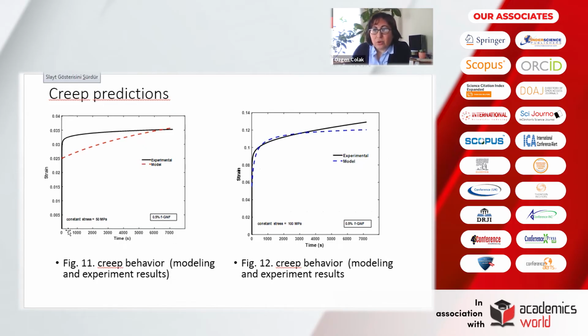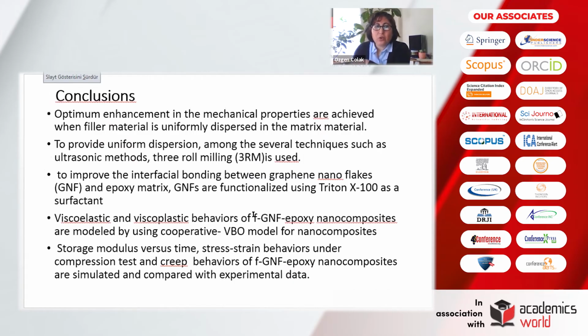And of course, as known, when you keep the stress constant in the creep, strain is increasing, and this change in the strain with time is observed, as you can see here. For the 50 megapascal case, there is some discrepancy. However, when we look at the 100 megapascal, a fairly good match is obtained in the change of strain with time. So these are the creep results.